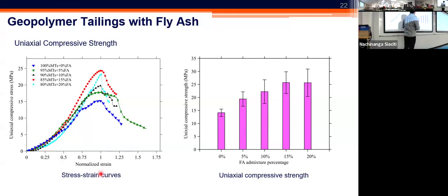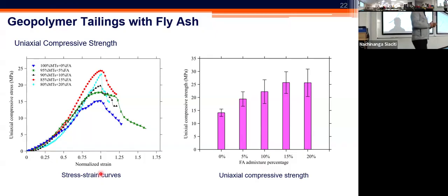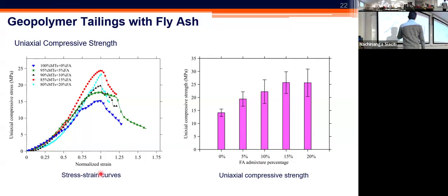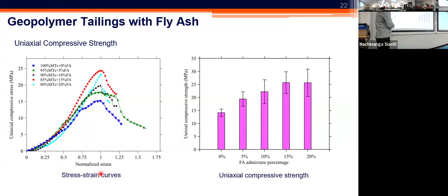So if you want to visualize a virtual line as the bare minimum strength requirement for these bricks that we are making, we usually consider 20 megapascal as the requirement for the strength. So one can argue that, well, if you get 15 MPa of compressive strength, that's probably insufficient. But as long as you can hit consistently 20 MPa and higher, ideally higher, then your geopolymerization has been successful for the purpose of the brick manufacturing.